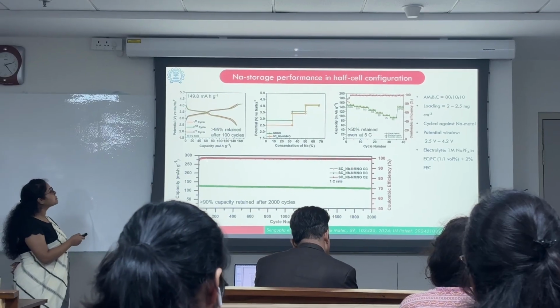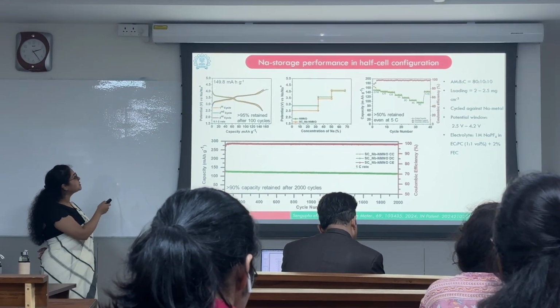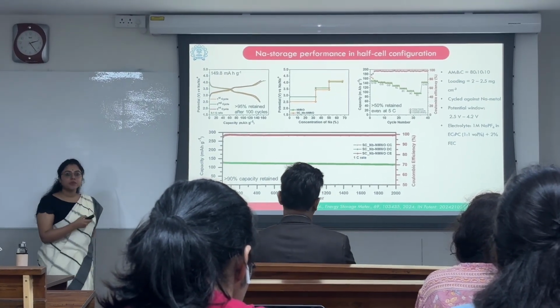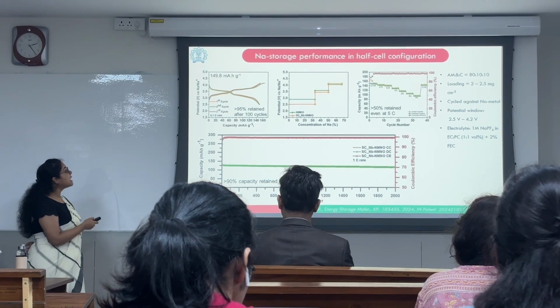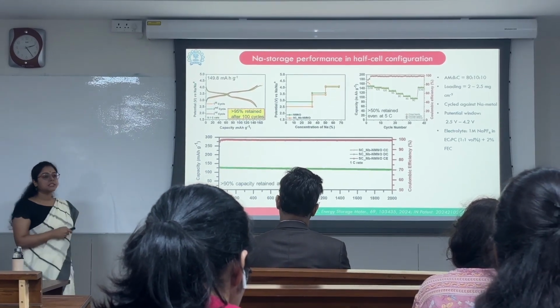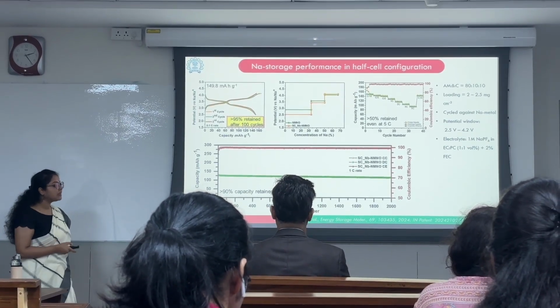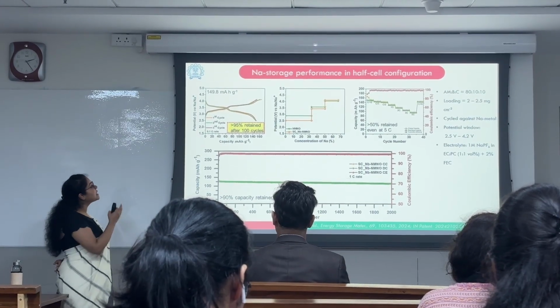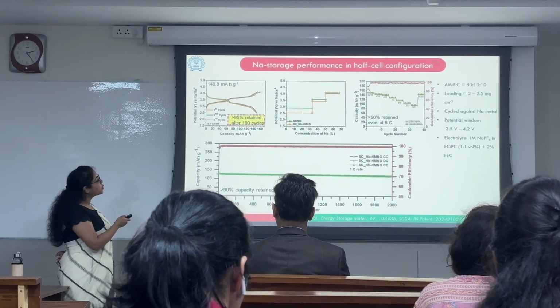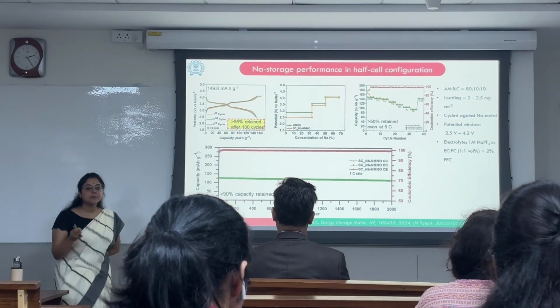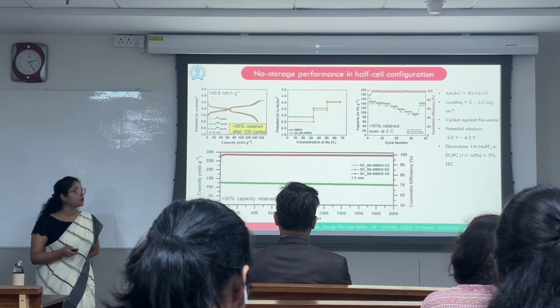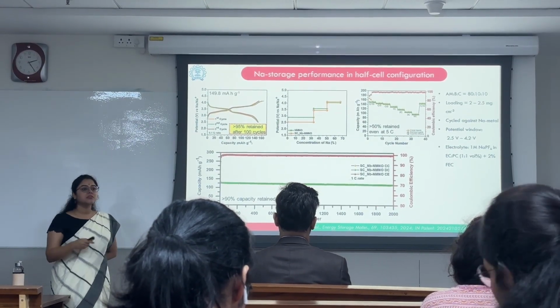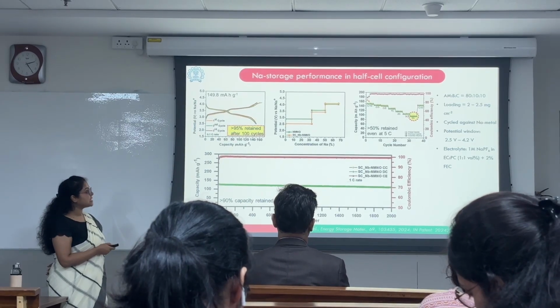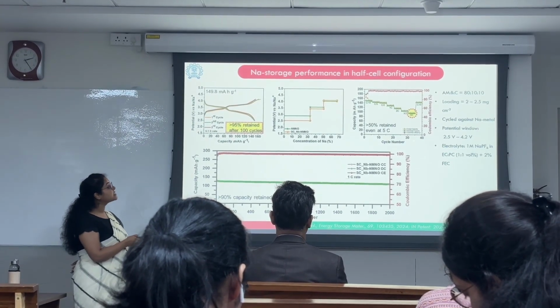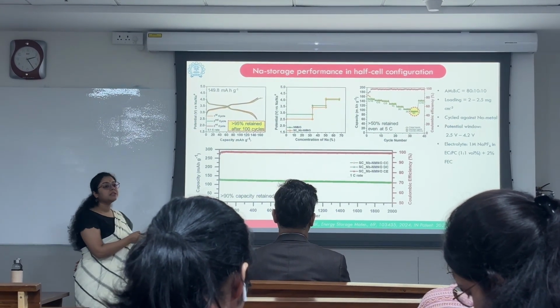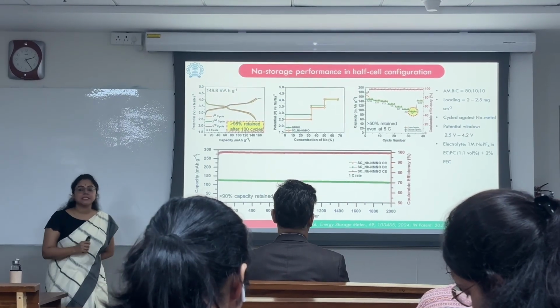And when cycled at a C rate of 0.1 C, we observed that the capacity was more than 149 milliamp hour per gram, with a capacity retention of more than 95% after 100 cycles. And through the DFT analysis, we saw that the niobium doped NMNO is stable over a wider potential window. And also we tested the reversibility through the rate capability test, which shows that even at a higher C rate of 5C, it can retain more than 50% of its capacity.